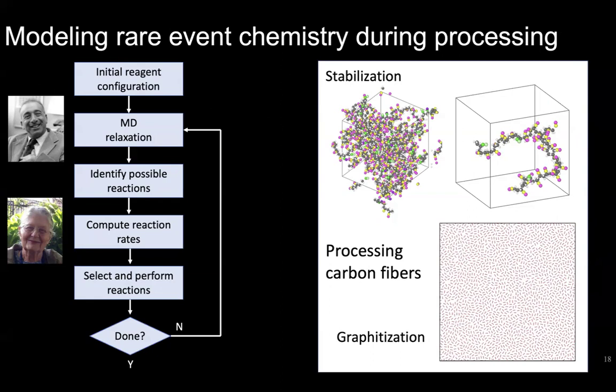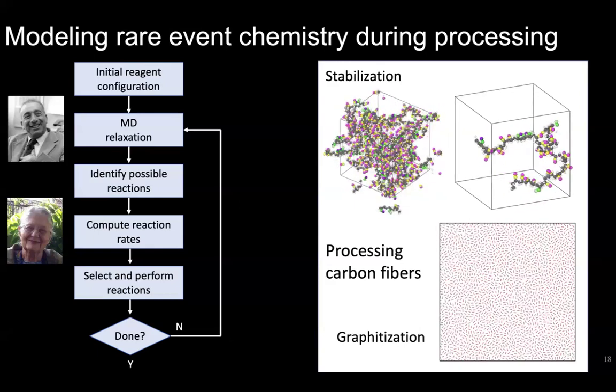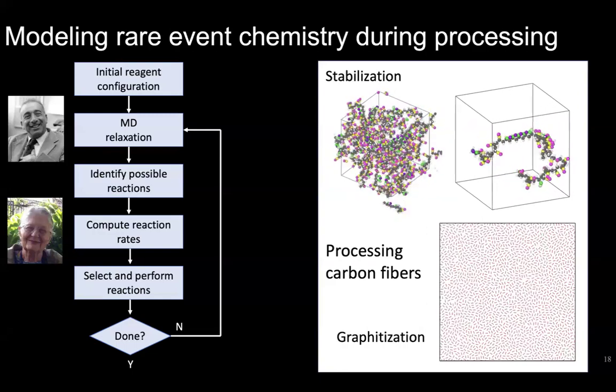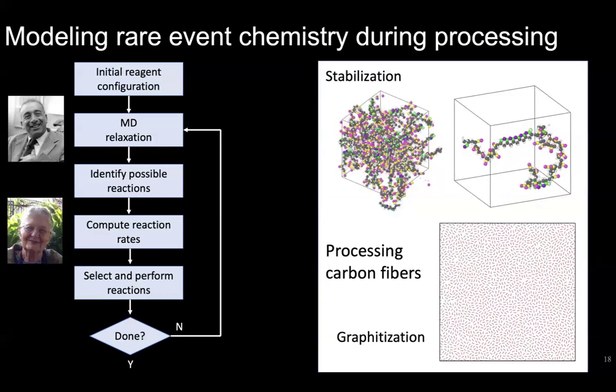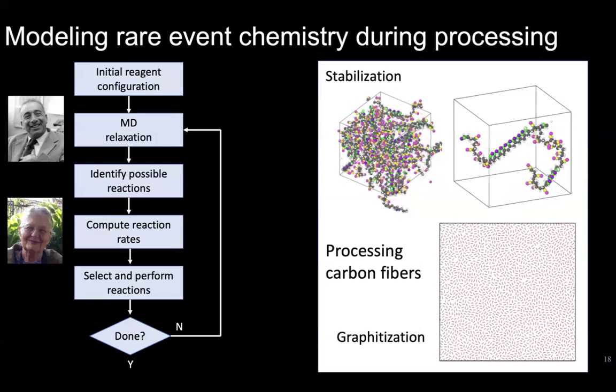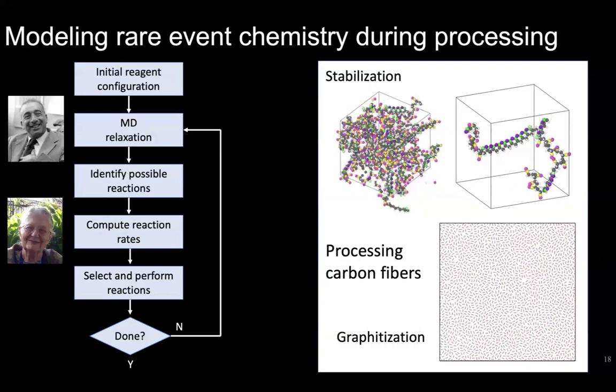And so what we did is we combined molecular dynamics with a Monte Carlo approach to, based on the local geometry, decide which atoms, which reactions are going to occur. So we do molecular dynamics, the polymer reacts, and then if you're close, not just a two-body but a many-body criterion, we form the bond. We force you to connect, okay? And we accelerate the chemistry that way. So you're going to see the birth of this. This is a single chain, and you're going to see here how this ladder structure is forming. Does that make sense? This is isolating a single chain in the system, and this is the full simulation.